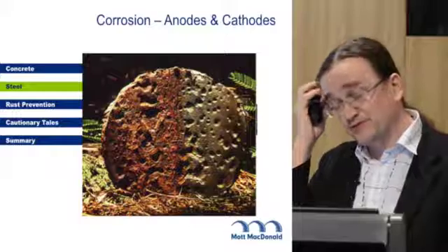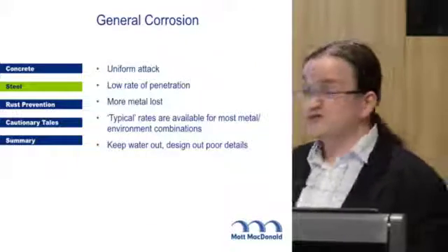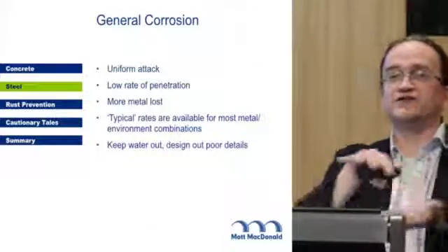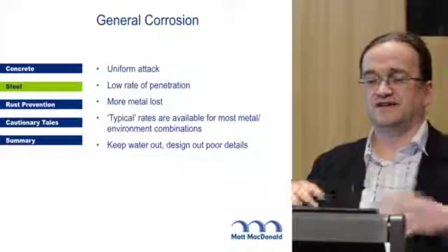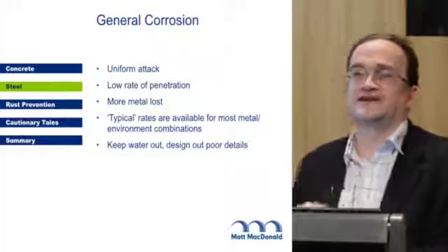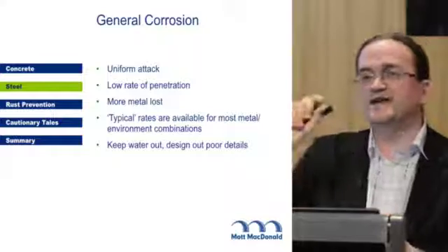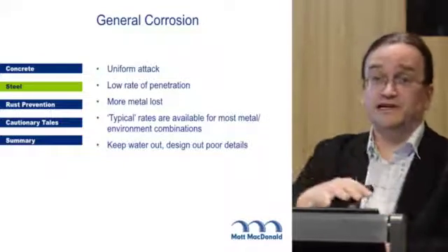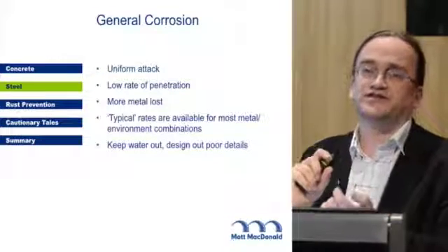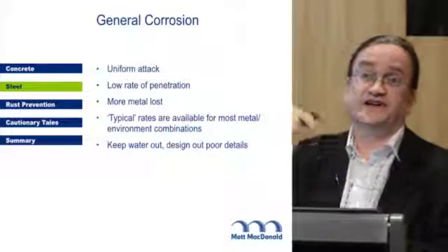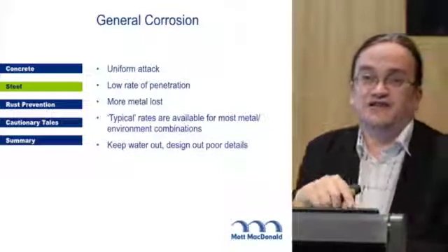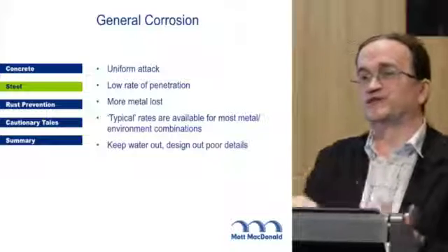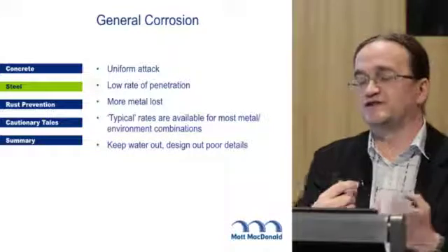There's a couple of different types of corrosion that are worth mentioning. General corrosion, basically the anodes and cathodes wander about the surface. So you get a fairly uniform attack. You don't get many holes forming until the metal's completely gone, but you do lose quite a bit of section. So structurally, the fact that there isn't a hole in it doesn't necessarily get you off the fact you've lost 2 millimetres off the perimeter of your beam, because that can be a significant amount of metal.